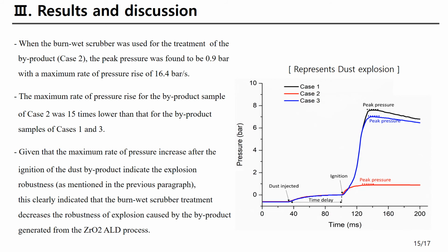16.4 bar per second. The maximum rate of pressure rise for the byproduct sample of case 2 was 15 times lower than that for the byproduct samples of case 1 and 3. Given that the maximum rate of pressure increase after ignition of the dust byproduct indicates the explosion robustness, this clearly indicates that the burn-wet scrubber treatment decreased the robustness of explosion caused by the byproducts generated from the zirconium oxide ALD process.